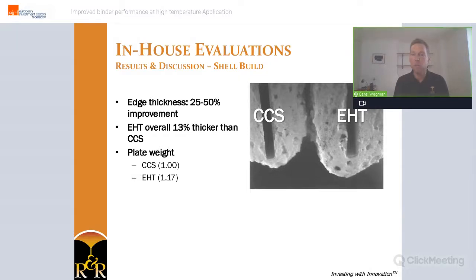The picture here shows the differences seen in the shell build at the edge thickness. You can clearly see the difference. Compared to the CCS sample, a 13% improvement in overall shell thickness was measured with EHT. Around the edge, a 25 up to 50% improvement was measured. The plate weight confirmed a 17% greater pickup of slurry with EHT as compared with the CCS binder, while the viscosity is lower. So obviously, this was considered beneficial, as a thicker shell will increase the load bearing capacity of the shell.